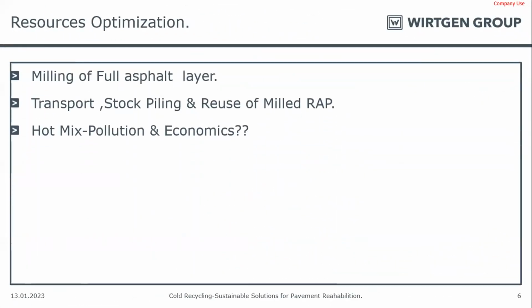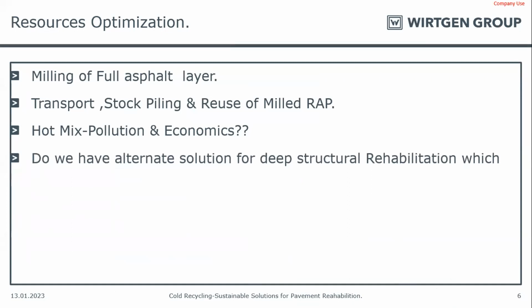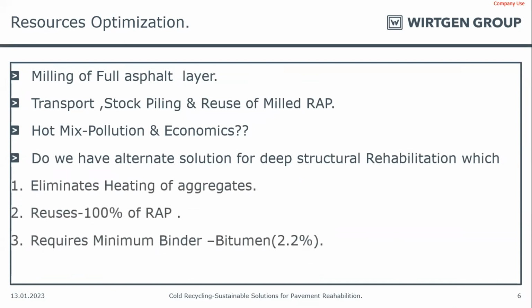Coming to resource optimization, as I said, one option of pavement rehabilitation is mill and fill. Mill the existing asphalt layer, take it back to the hot mix plant, and use 30% of it back into the system. But there is one more option where you can get 100% RAP back into the system. That is called CIPR, cold in place recycling. This ensures 100% reuse of RAP back into the system. We do it in situ. It eliminates any heating of the existing aggregates, and we require only 2.2% of bitumen as binder and 1% cement as filler.